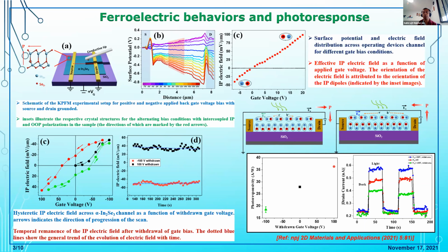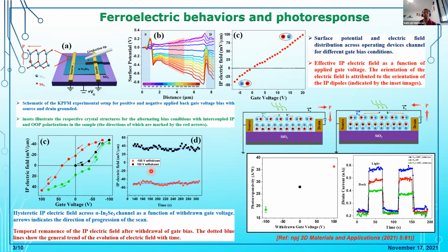Then we withdraw the gate voltage and map the devices. We have a very nice hysteresis loop from the Kelvin probe measurement, and it also has a high retention over the time scale. Then we check these devices for the photoresponse behavior. First, in the fresh state we measure the responsivity, which is about 30 amperes per watt. Then we pulse the device with a positive gate voltage, say 100 V. Then we withdraw the gate, and we again check the photoresponsivity and do similar things for negative pulsing. So we see for both cases, the pulsing changed the photoresponsivity quite a lot.